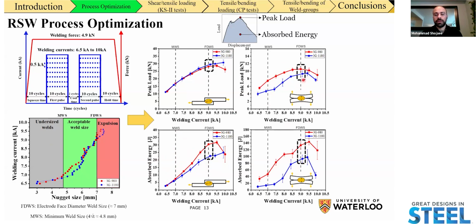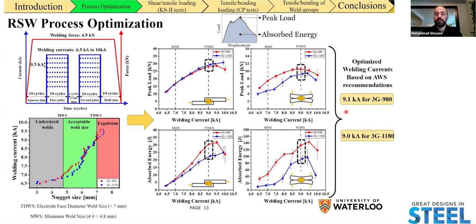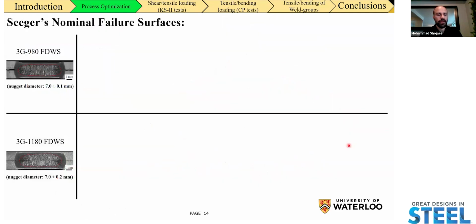And the highlighted welding current is actually going to be the optimized condition with the highest amount of load bearing capacity and energy absorption capability. And the welding current selected is also written on the right hand side, which was 9.1 and 9 kiloamps for 3G 980 and 3G 1180 respectively. Now you can see all the optimized electrode face diameter, weld size, and the cross-sectional view of both steels. We're having a nugget diameter of 7 millimeter for both cases. So any changes or differences that we see in terms of mechanical performance is not going to be really related to differences in nugget size.